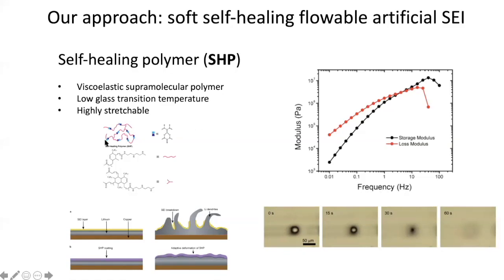That's because of the polymer network that we design. It's held together by these weak hydrogen bonding. So the molecules, even though the film looks like a solid, in the molecular scale, these red chains are exchanging with each other, and these clippers can break and close in a dynamic fashion. So these red polymer chains are constantly exchanging in the molecular scale. That's why when there's a non-uniformity, when there's a hole, the polymer can actually fill the hole on its own because it's actually mobile.